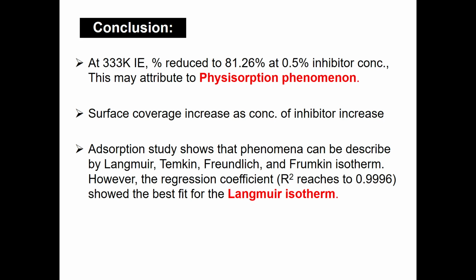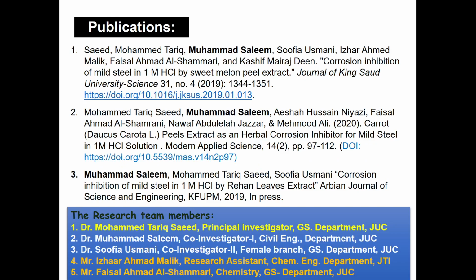However, the best regression coefficient value was obtained in the case of the Langmuir isotherm, and the study shows that sweet melon peel can be utilized to prepare a herbal corrosion inhibitor, which is safe and environmentally friendly, to protect the metal, and it gives very good results. Further study can be continued on this to find even better efficiency.